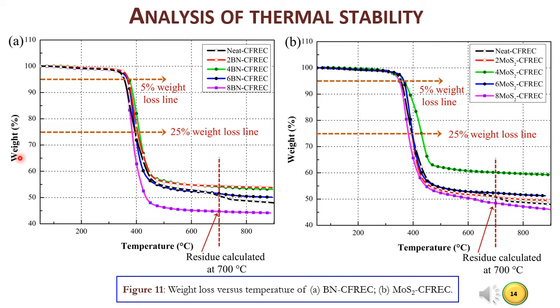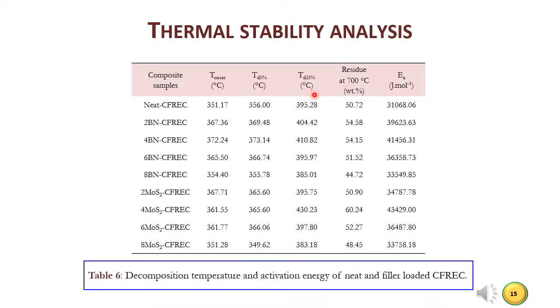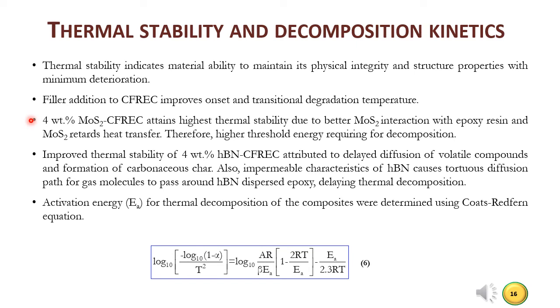Thermal mass stability and decomposition kinetics of each composite are studied. The figure shows weight loss as a function of temperature. Filler addition to CFREC improves onset and transitional degradation temperature. Neat CFREC exhibits 25% weight loss at 395 degrees centigrade, 4 MoS2 CFREC at 430 degrees centigrade, and 4BN CFREC at 411 degrees centigrade. This indicates increase in degradation temperature of 4 weight percentage filler added composite. 4 MoS2 CFREC achieves highest thermal stability due to improved MoS2 interaction with epoxy and heat reduction due to lubricant property. Improved thermal stability of 4BN CFREC is attributed to carbonaceous char formation and impermeable characteristics of hBN, which cause a tortuous diffusion path for gas molecules.